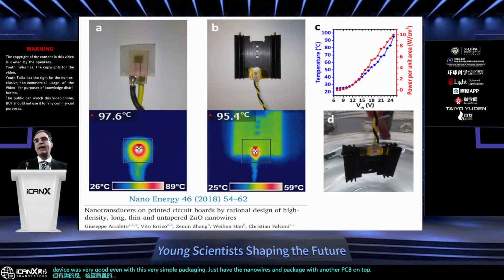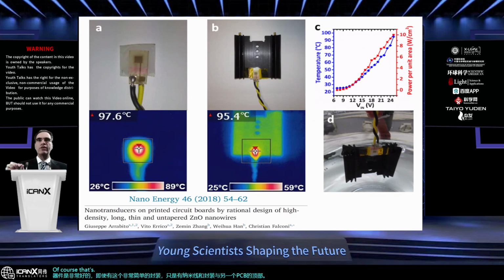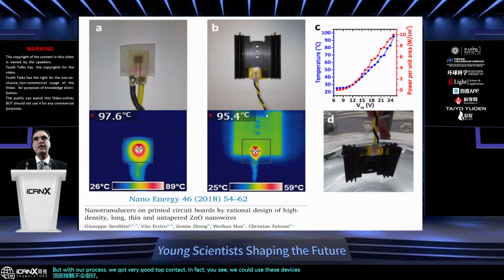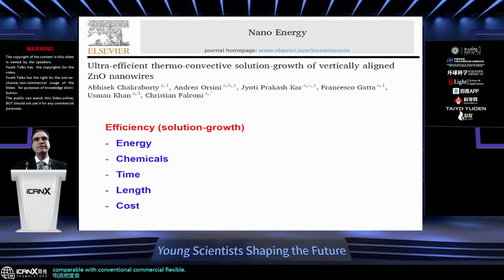So of course, that's why we didn't want the tapered nanowires, because otherwise the top contacts would not be very good. But with our process, we got very good top contact. In fact, you see, we could use these devices also as flexible heaters with remarkable current densities that were comparable with conventional commercial flexible heaters.